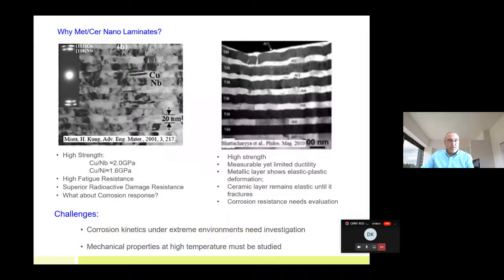Basically, if you look at the literature, you would notice that nanolaminates are not something new. People have been going at it for a while. This is a picture from 2001. Here you see copper and niobium layers that have been deposited on a substrate, and these are all about 20 nanometers thick each. The outcome of applying these types of coatings and then stacking them up to make a more fundamental material is that you can achieve high strength. If you have a copper niobium combination, you can get strengths of up to 2 gigapascals, which is very strong. It's almost close to the theoretical strength that you can achieve in these kinds of metals. Or you could do copper nickels and you can get strengths close to about 1.6 GPa.